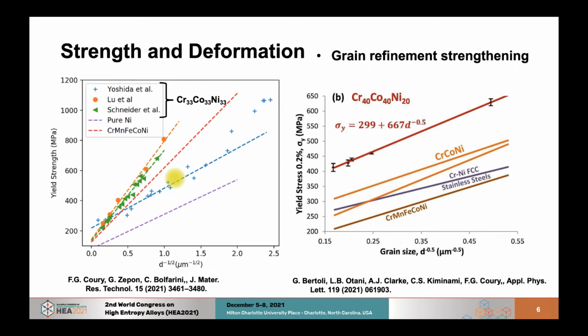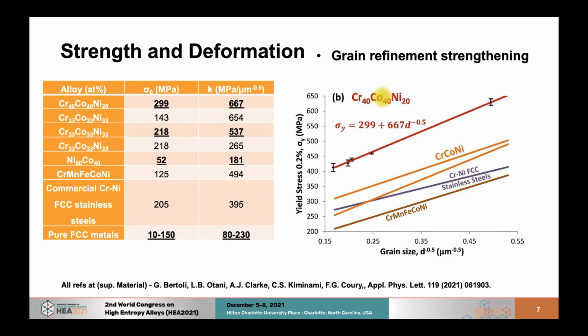And on the non-equiatomic compositions, also some studies have been performed. I'm giving here an example of a higher chrome alloy, and I'm going to talk a lot in this presentation about higher chrome-containing alloys. And basically summarizing these results in this table, what we see is that by increasing chrome, we get a higher intrinsic yield strength, the sigma 0 term, and also higher Hall-Petch grain refinement constants. So this is very interesting and points to the direction of higher chrome contents being something interesting.